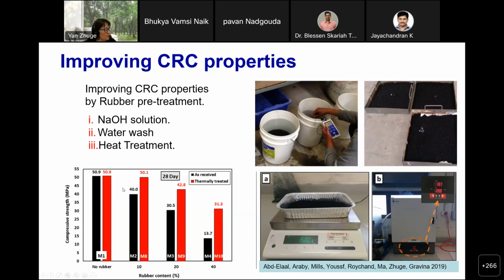This summarizes the 28-day compressive strength improvement. You can see the reference group without any rubber, and then 10%, 20%, and 40% rubber. The red color is the thermal treated samples. You can see the compressive strength was improved significantly, especially for the higher rubber percentages of 20 and 40%. It increased from about 13.7 megapascals to more than double, up to about 31 megapascals. So we think this heat treatment is an economical, cheap, and simple way to improve the properties of crumb rubber. This work was also published in Construction and Building Materials in 2019. Those are some very interesting results.